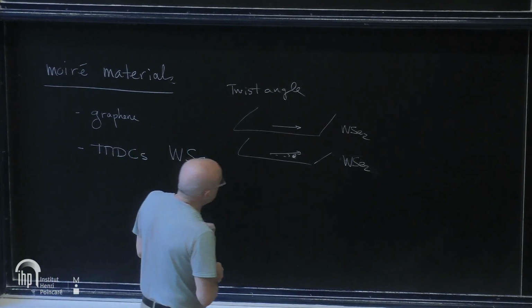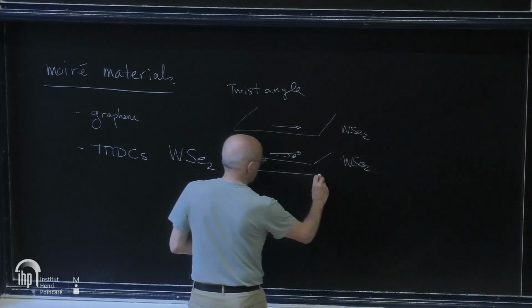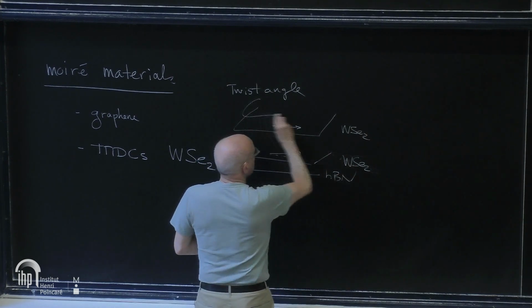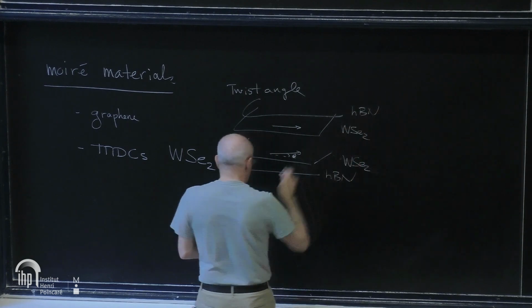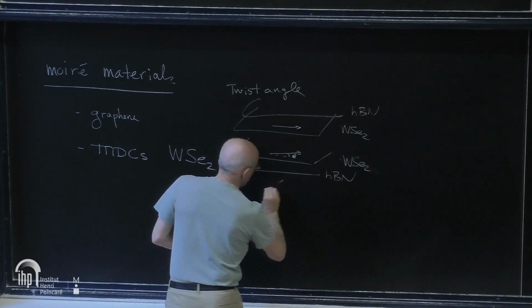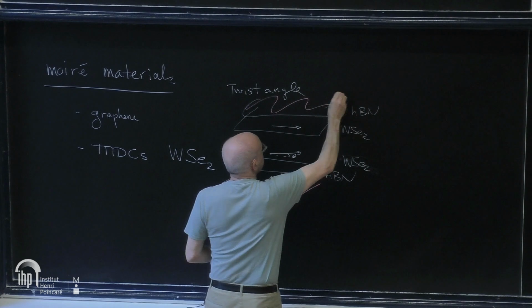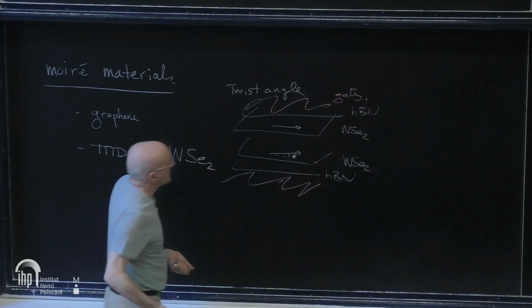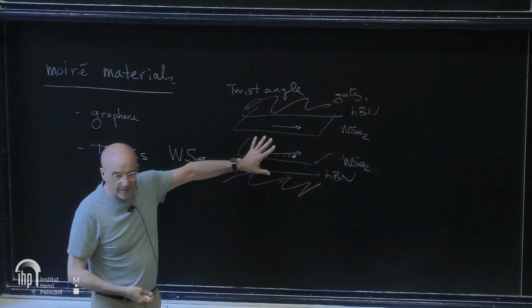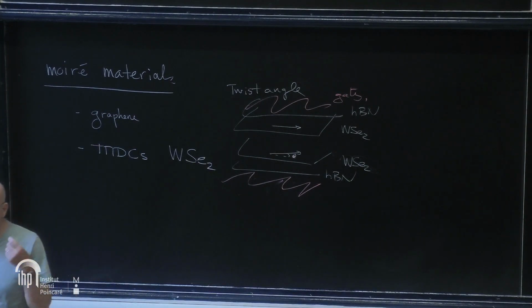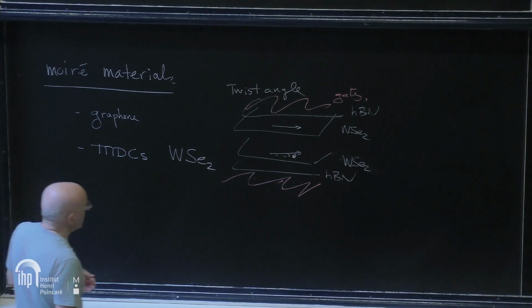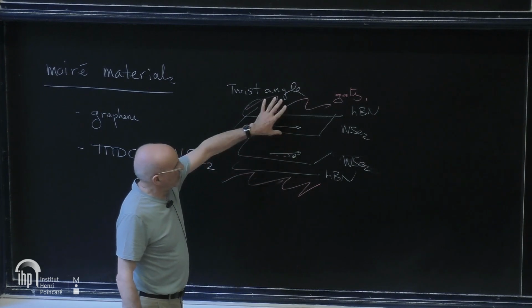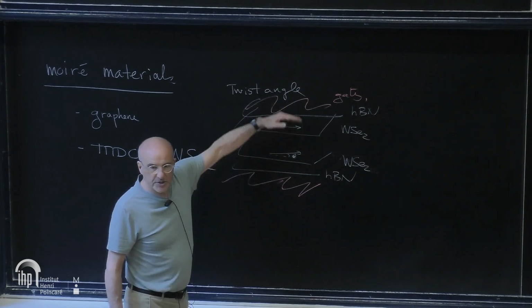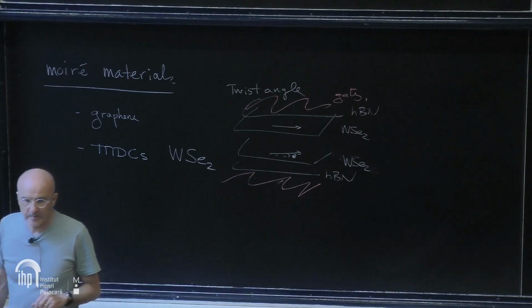So the actual devices look something like this. Here they would put some hBN, for example, hexagonal boron nitride, and some gates, some electrostatic gates. And these systems become very controllable platforms in which you can control the bandwidth, the electronic structure, and to some extent, the strength of the interaction by acting either on the twist angle or on the electrostatic potential of the top or bottom gates.